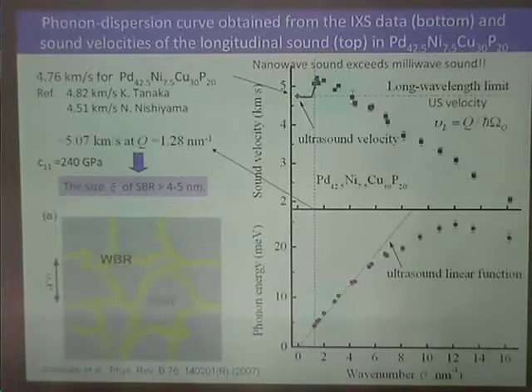That's only if you assume that this structure has a very well-defined Q, right? For instance, if you have a single delta function, it carries all the Qs. So in this case, the difference between the ultrasound and the X-ray frequency alone is enough to explain the difference. So I'm not sure about the Q value, how valid the Q value is, or how valid it is to extract xi from this Q crossover. So this object has this Q component. It does not mean that it's the only component.